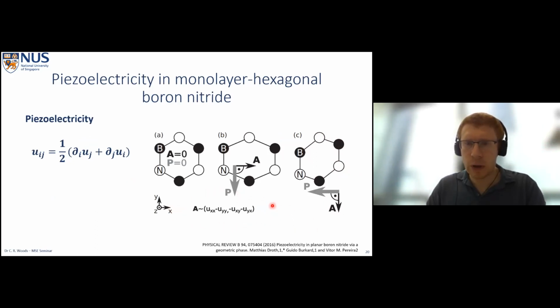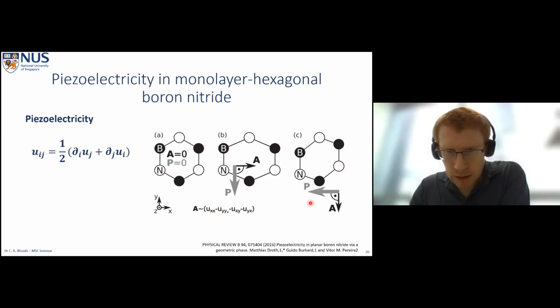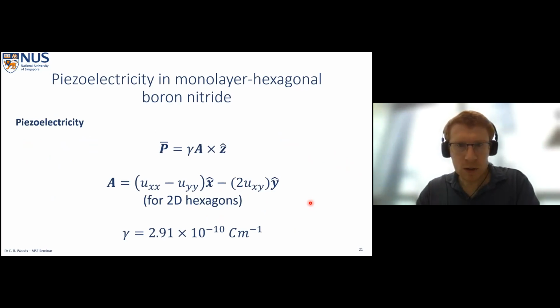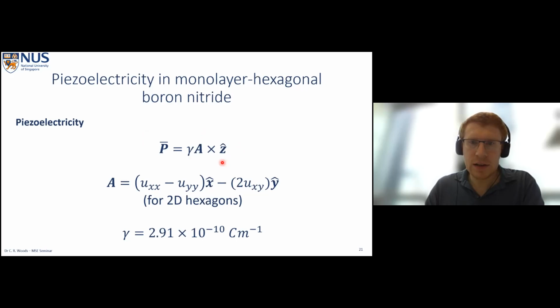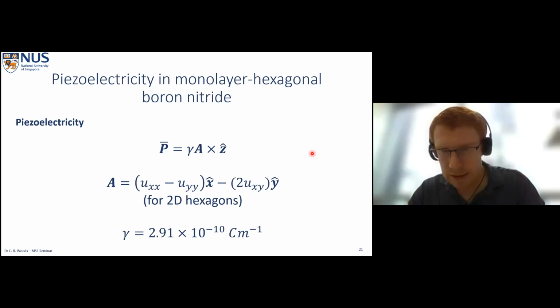And this is generally given by this vector potential for 2D hexagons, where U_ij is the strain tensor for the system. And the vector potential can be simplified for the 2D hexagons. Right, so the polarization here is then given by the vector potential times the piezoelectric constant for hexagonal boron nitride, crossed with the z hat, crossed with our out of plane unit vector.